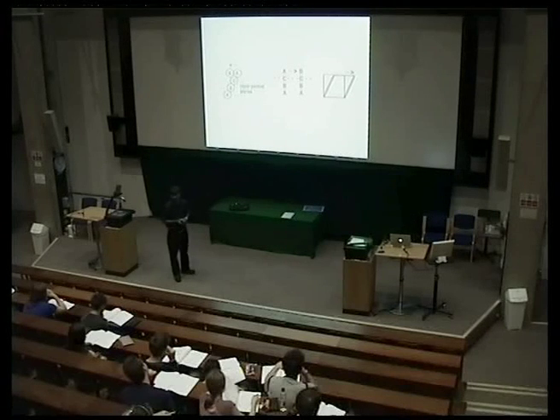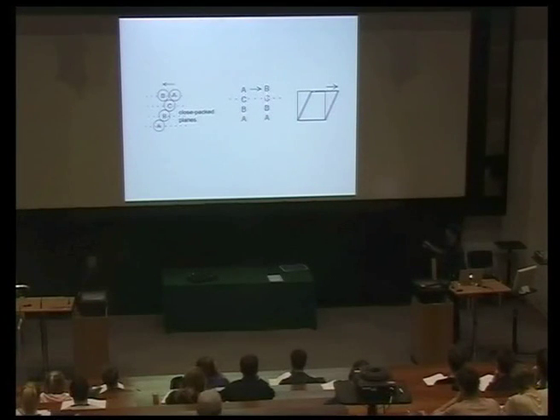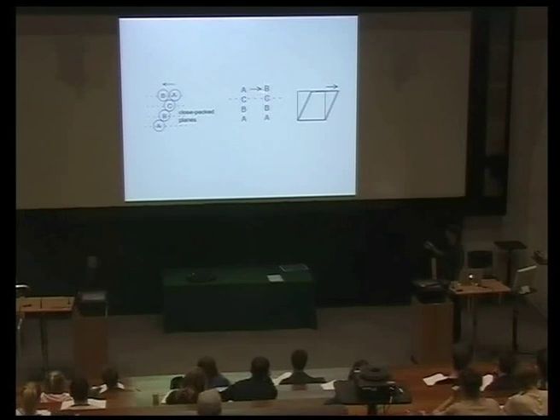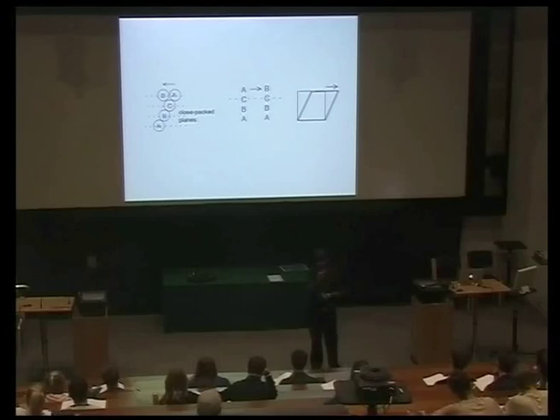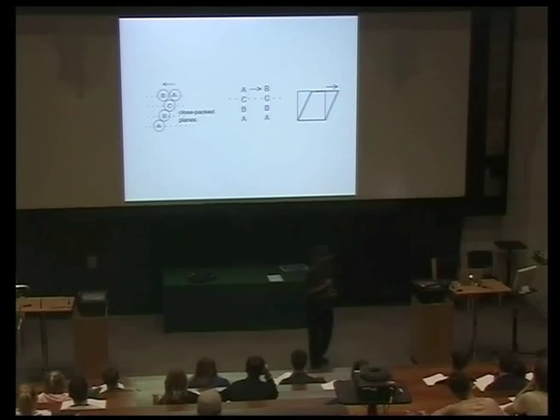What we are doing is creating above this region another cubic close-packed structure, but it will be in an orientation which is reflected about the twin plane. We know from this diagram the spacing of this plane. All we have to do is determine the distance between an A hole and a B hole on the close-packed layer to calculate the magnitude of the shear. The magnitude of the shear will be that displacement from A to B divided by the spacing of the 111 planes.